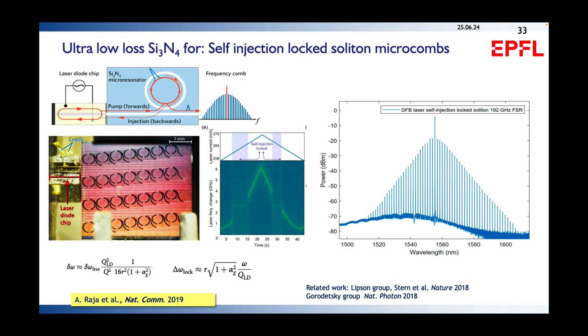Now, another example that has been really enabled by these very low losses that we have is the pump laser. So evidently, pump lasers of several watts are precluding use actually in compact devices. So here is some work actually that shows that if you use just a DFB, a distributed feedback laser, that has an output power of typically 10 to 100 milliwatts, and if you injection lock that to one of the silicon nitride resonators, the slight reflection that you have from residual imperfections leads to two effects. The first is actually it will send back some of the power into the laser. This leads to a phenomenon called self-injection locking, where the free-running DFB linewidths get suddenly dramatically narrowed, and I'll mention actually how much a bit later in the presentation. But there's something else happening. You can also, on top, generate actually a soliton. So these are so-called self-injection locked soliton microcombs that now actually have a form factor of just a few square centimeters, and also can be driven here with electrical powers that are at the watt level.